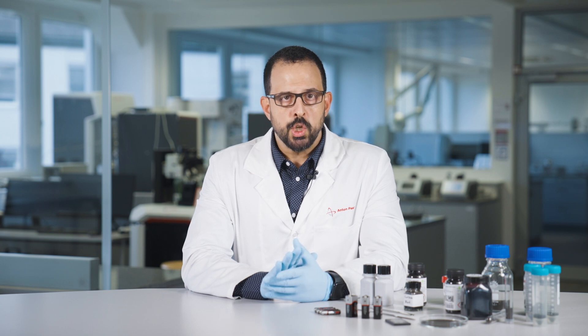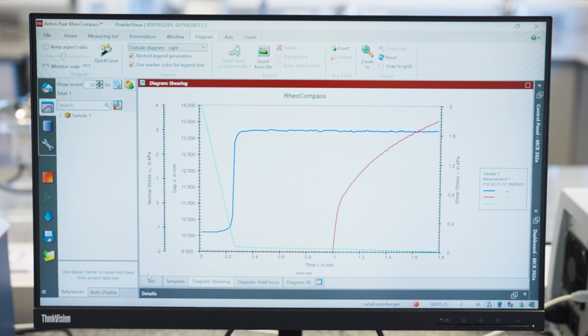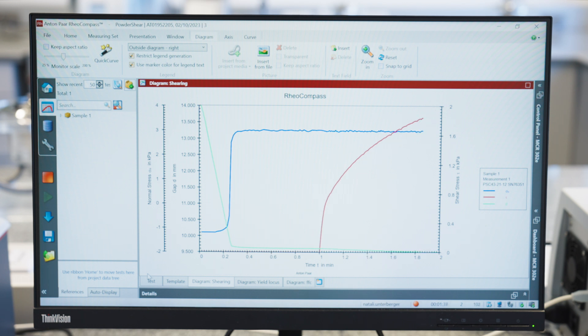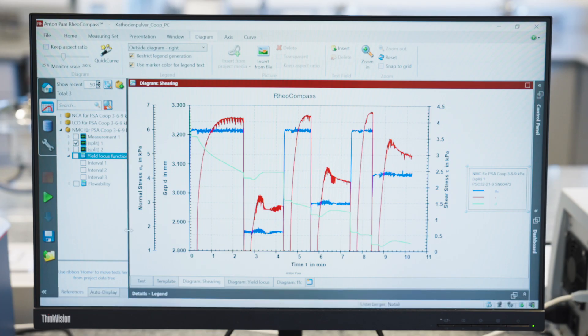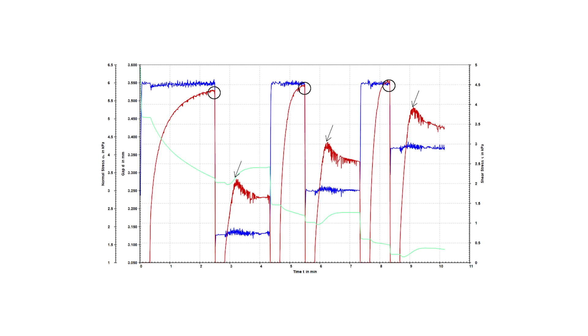The consolidated powder is sheared at a rotational speed of 0.005 RPM and the analysis will stop after about 10 minutes. During shear of the electrode powder, the rheometer software records and displays any changes in both shear stress and gap at the applied normal stresses. This not only provides information about the failure behavior, but it also allows the investigation of dilatancy effects. The shear curves shown here resulted at a normal stress at pre-shear of 6 kPa, marked with circles. The shear to failure points are generated within the range of 20–80% normal stress at pre-shear, marked here with arrows.